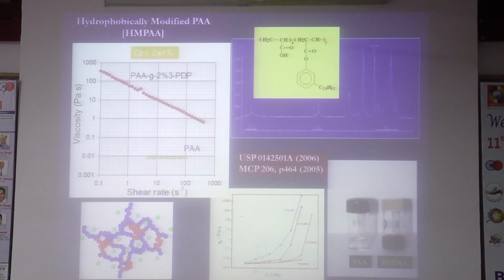So I get a polymer which is modified with this cashew nut shell liquid. And you can see here how the viscosity changes, 1, 2, 3, 4. Four orders of magnitude change in the viscosity. For example, just the polyacrylic acid shows a liquid here. After modification, you can see a gel. The viscosity has gone up so high. So with a very small modification, you get a very big change in the property. So this is one example, and we are trying to illustrate it.